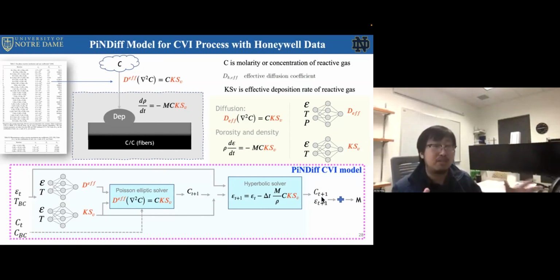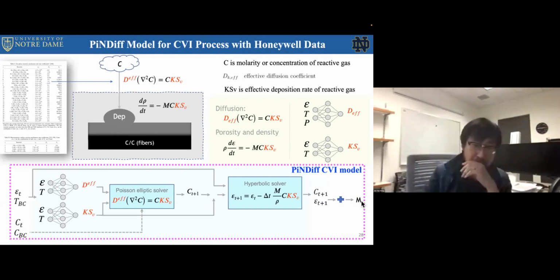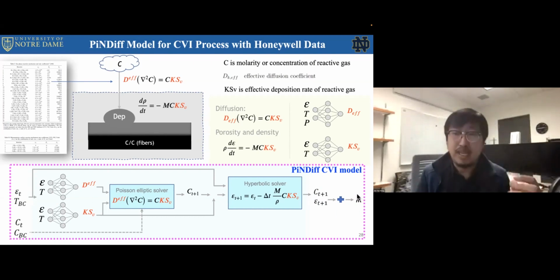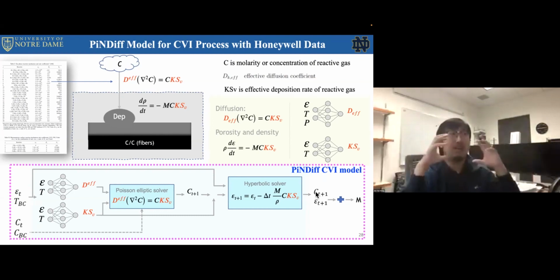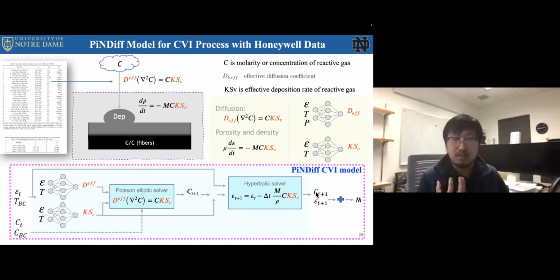So here the t+1 doesn't mean the numerical time step. It can go a little bit further, so we have faster inference speed. And also it describes the transition of the molarity of the reactive gas from t to t+1. So in this way, we can also get the weight or mass of my samples. So that allows us to integrate the data, like the weight. We can measure weight instead of measuring the porosity or the molarity of the gas. Those are usually not available, but it's very easy to get the weight. So basically, in the manufacturing process, after all, we take out the samples and measure the weight, and we get some weight measurements. Okay, so we can use that to train our model.